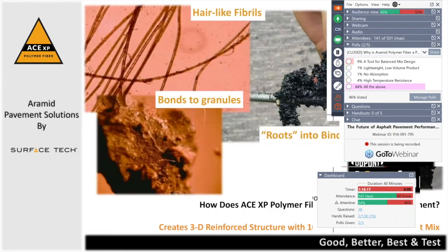And because of its high temperature resistance and because of its high tensile property and also high modulus, this product gets into the mix, creates a three-dimensional structure with those 10 million fibers, and really gives you a full-depth reinforced asphalt section. So you're not trying to reinforce it from the bottom with a fabric or a grid, you're actually reinforcing that entire depth of your asphalt overlay or full depth pavement, whichever you decide to use it in.